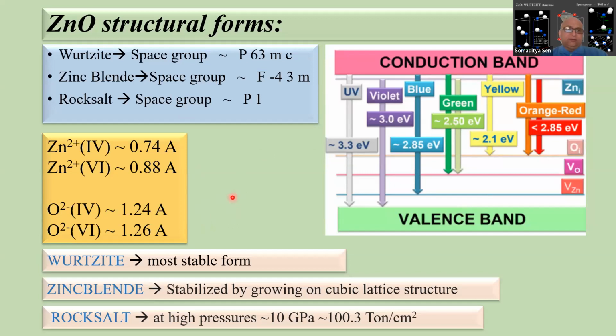Now, in zinc oxide, zinc is generally in the wurtzite and zinc blende structures, in the tetrahedral geometry. The tetrahedral geometry has a coordination of 4, and the ionic radius of the zinc atom will be 0.74 angstrom. Whereas in the tetrahedral geometry, the oxygen is also tetrahedrally arranged, and it will have an ionic radius of 1.24 angstrom. But in the rock salt structure, it is in the octahedral geometry, which is surrounded by 6 oxygen, and the ionic radius will be much larger than the tetrahedral, 0.88.